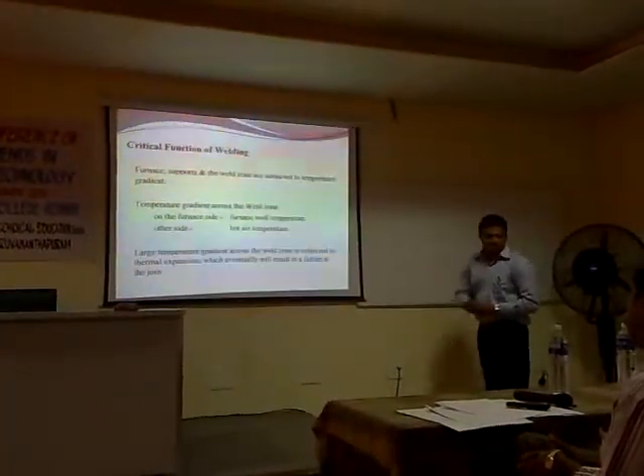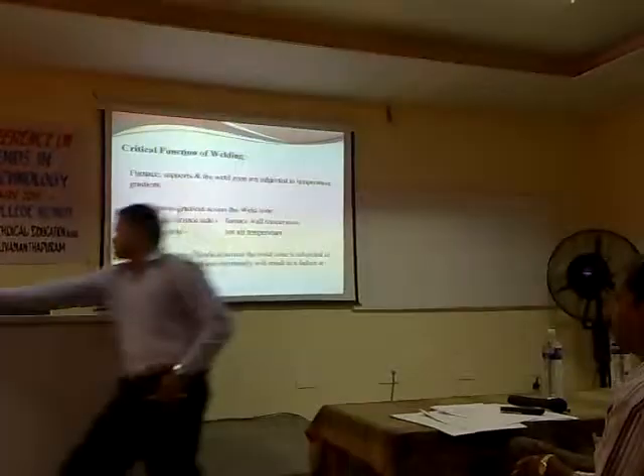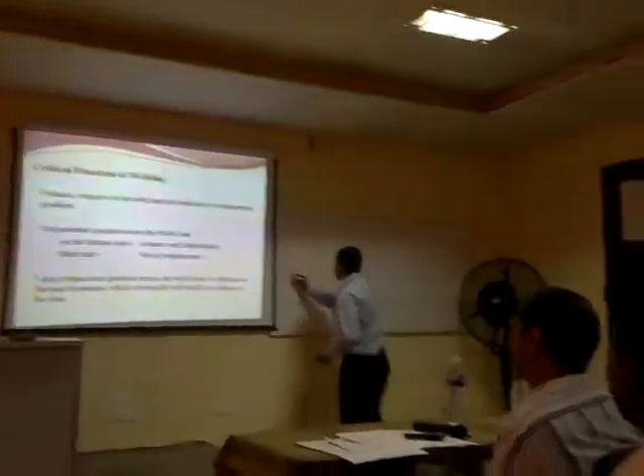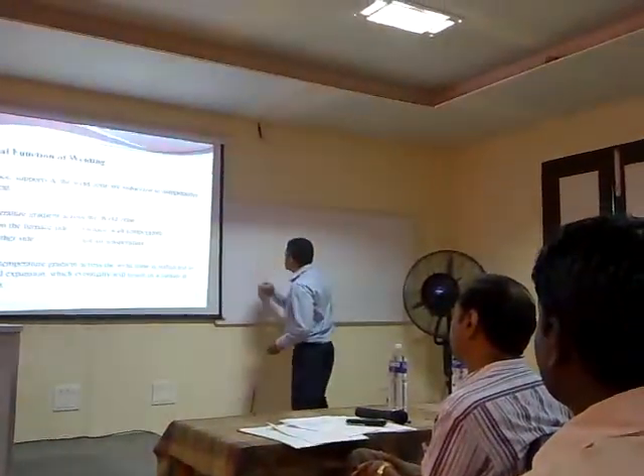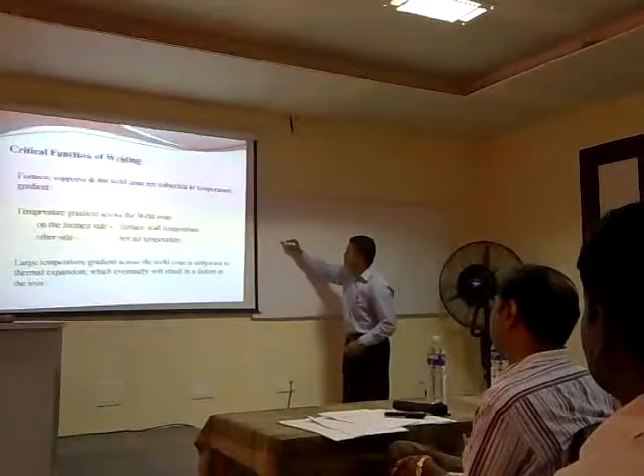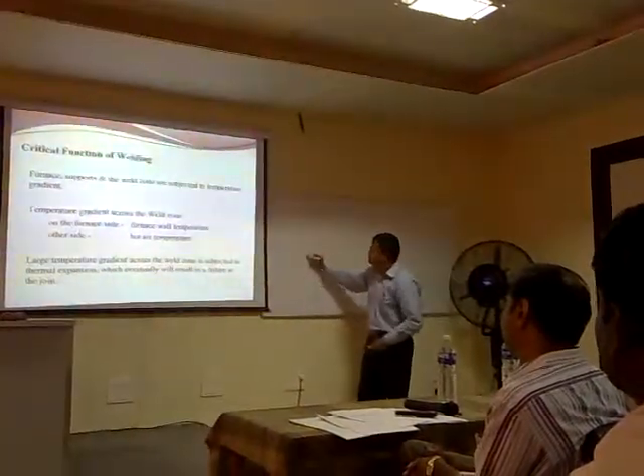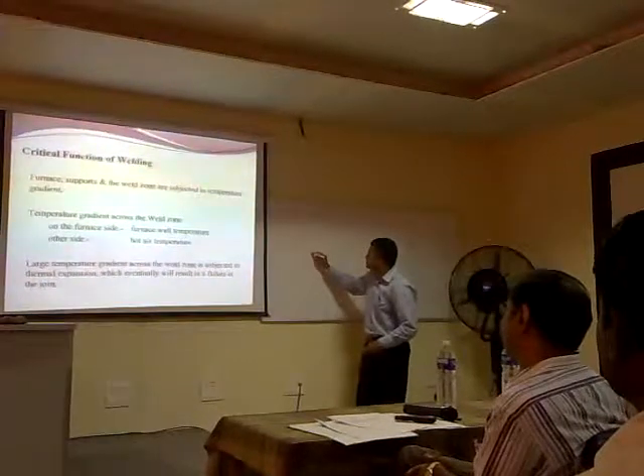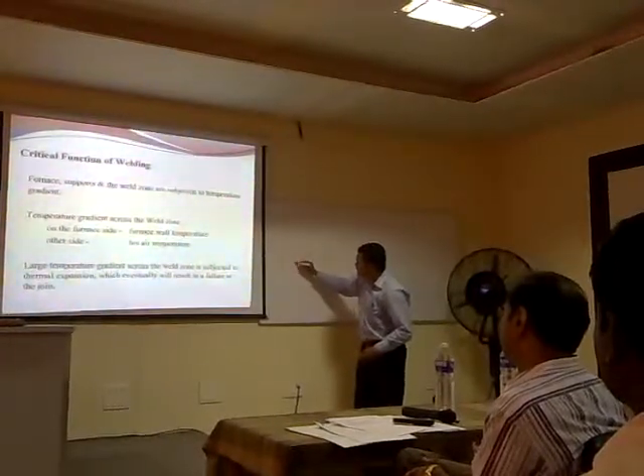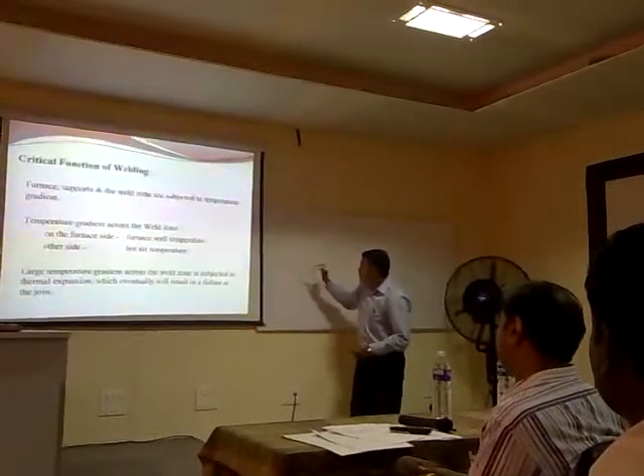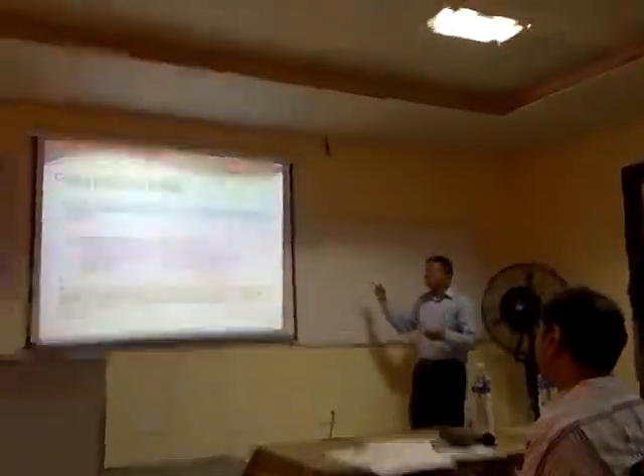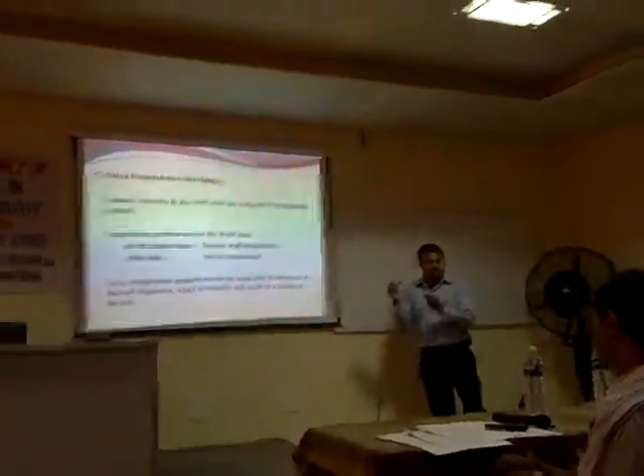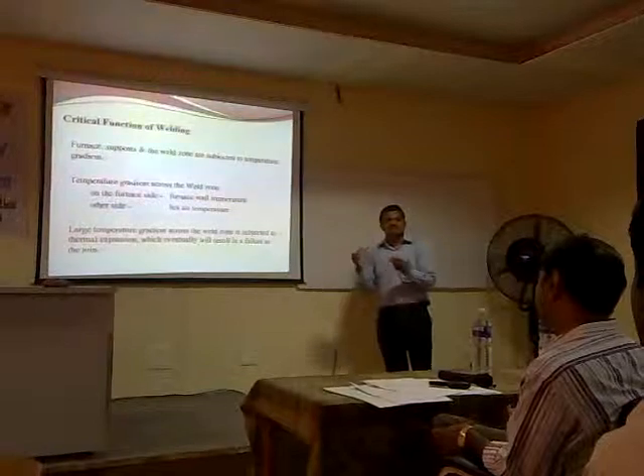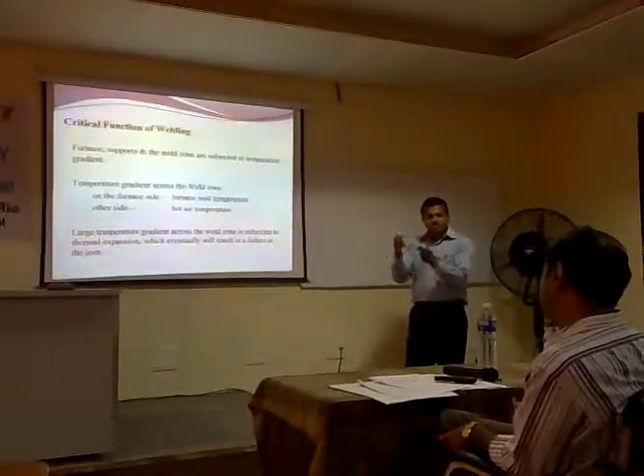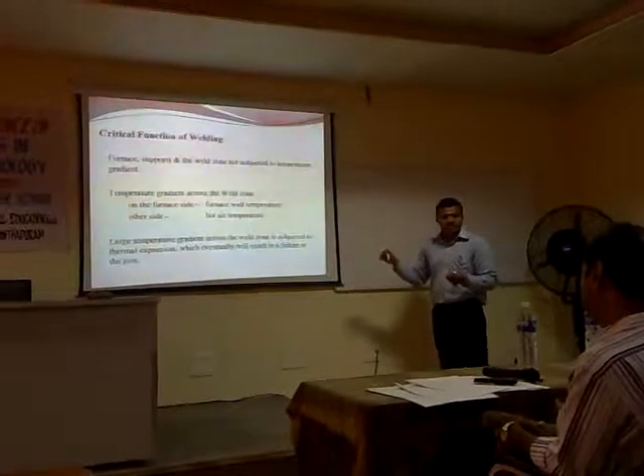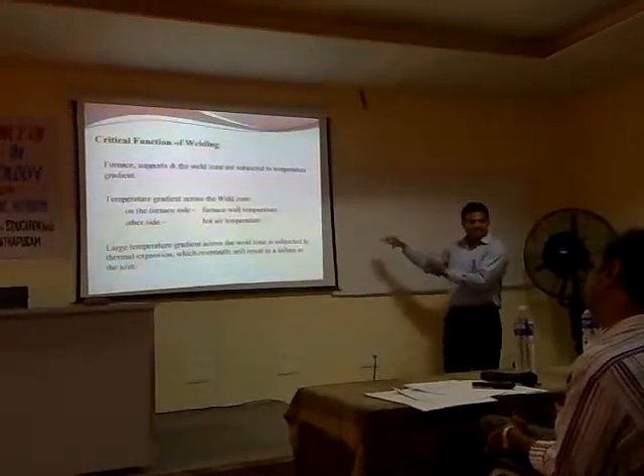Now, as I told you, if we consider this as a pressure vessel, then the temperature over here, let's take it as 600 degrees Celsius, and outside temperature let's take as 20 degrees Celsius. Then across this thickness, welding is done over here. Across the welding zone, the temperature difference that occurs is around 580 degrees Celsius. So a very high temperature difference occurs across that particular zone. Due to this high temperature difference, very high thermal stresses are induced. And because of these stresses, thermal cracks are observed in this welding zone. So I am working on this particular zone.